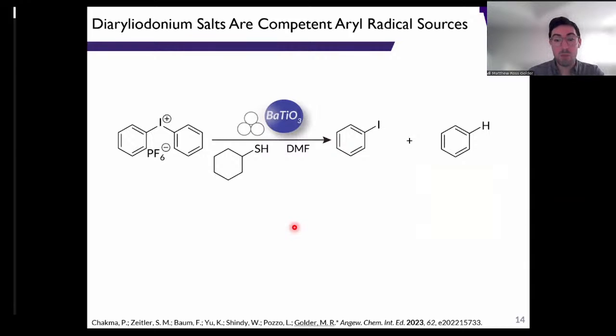Mechanistically, we are confident that the diaryl iodonium salt is our initiating species. We can perform the mechano-redox reduction of these diaryl iodonium salts in the presence of an H atom transfer agent, such as this cyclohexyl mercaptan. And we would expect the generation of both iodobenzene and benzene following H atom transfer. And that's exactly what we see.